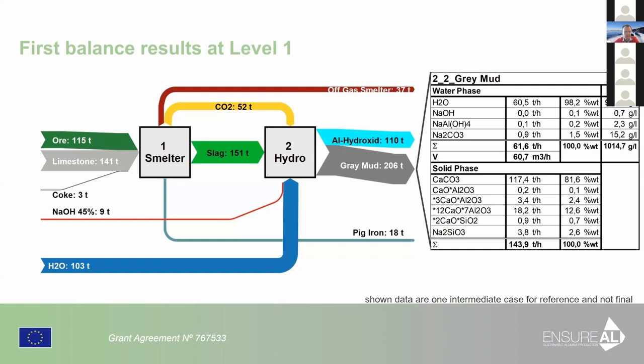in goes out. At the current assumption, we would produce 18 tons of pig iron and 110 tons of aluminum hydroxide in wet conditions. So that's the main basic streams, and as you can see within the balance, we have much more data available. So I really know the moisture, trace elements in the water phase, and also the solid phase and the composition of the gray mud, for example.